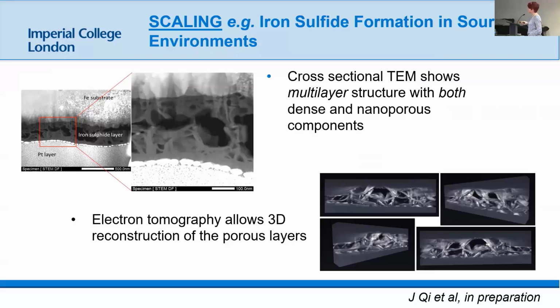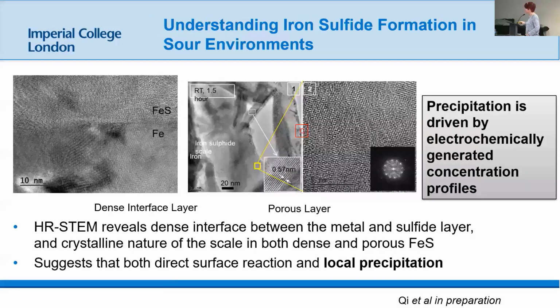And these are just some data from our lab on forming iron sulfide in a really controlled way, and then looking at the type of structures that you form. And what you see when you do that, you see these extraordinarily complex nanoscale structures that are formed when iron dissolves and it meets some sulfur in the environment. And, of course, what you get depends massively on all the different parameters that are existing in the system, the temperature, the flow, the concentrations. But it's not a simple layer of iron sulfide. And actually, when you go in a little bit more closely, you can see right at the iron sulfide interface, it's beautifully coherent. And then we form these nanoscale features that are perfectly crystalline iron sulfide.